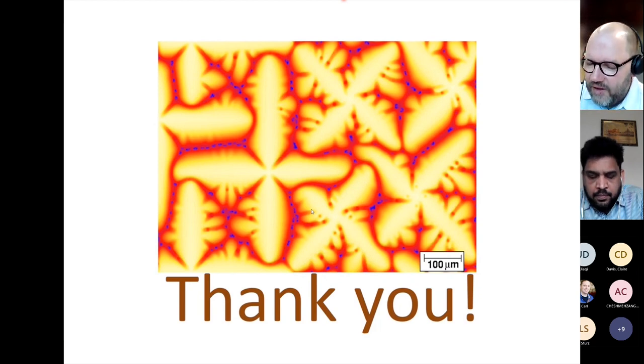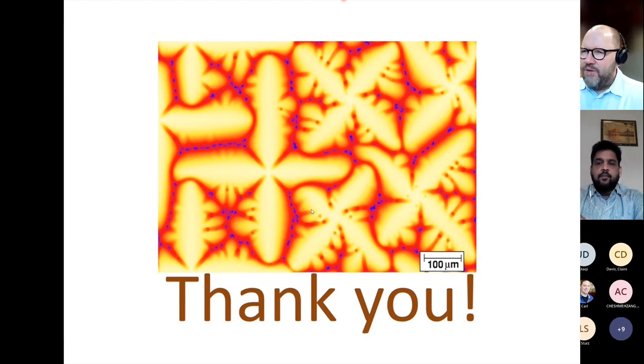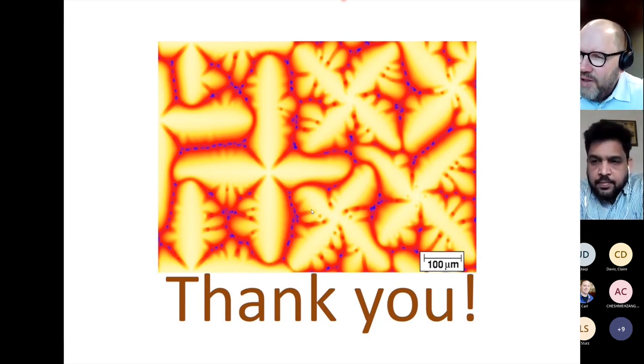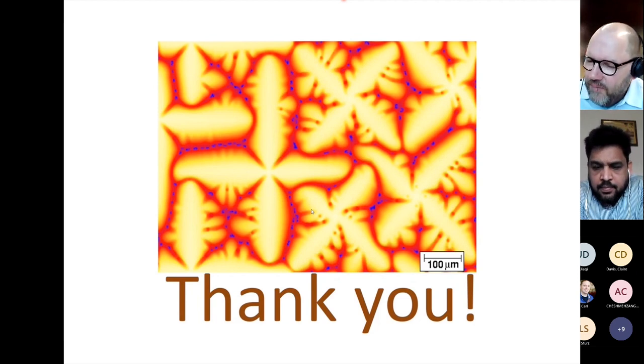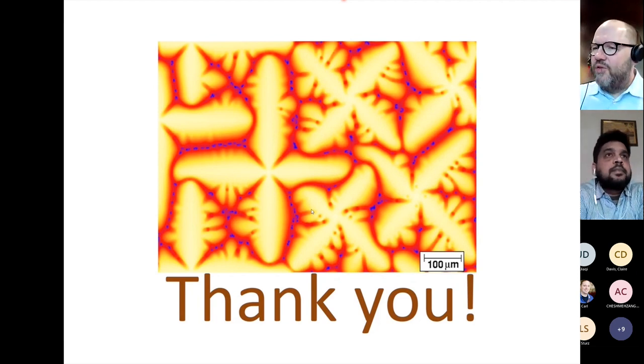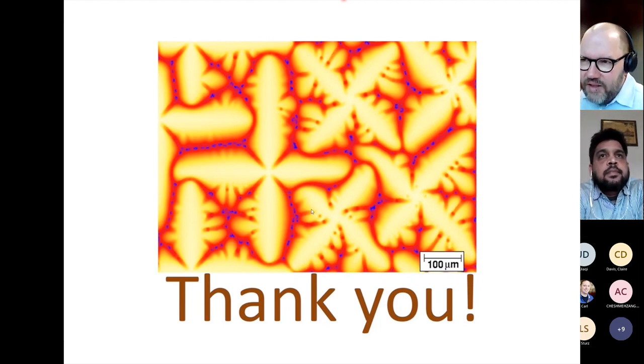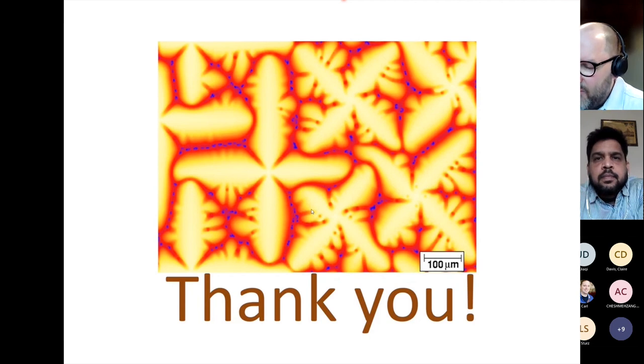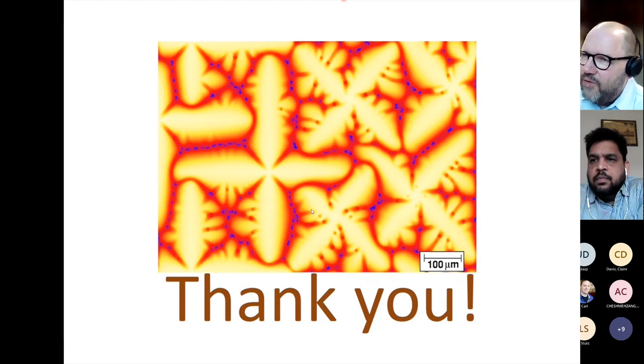Your other question is then, of course, we do the cooling. The material is not homogeneous. It has microsegregation and it has phases which wouldn't be there in equilibrium. So that means there is a lot of energy stored in the system that gets released during the heat treatment. And this is what's driving the diffusion of the elements across the structure. So that energy gets dissipated during the solution heat treatment, when we activate the diffusion, the equilibration of the concentration gradients and the dissolution of the unstable phases.